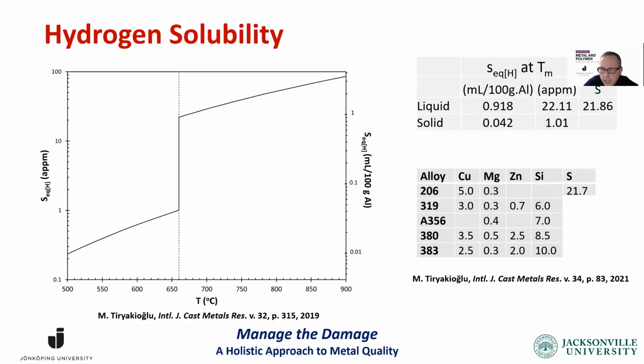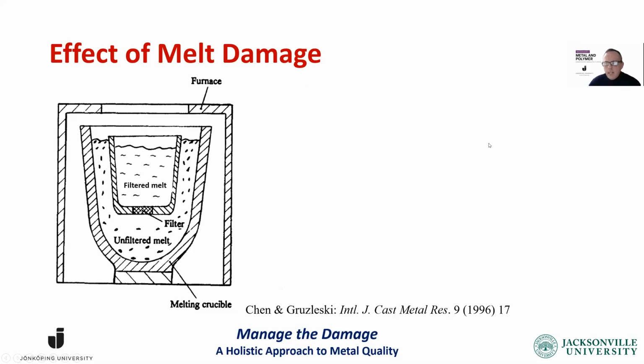When it comes to aluminum silicon alloys like 319, 356, well, we have a much smaller problem. About 3 is what we're talking about. So that gap that we've all learned about is not that big. And when it comes to these die casting alloys, I found something that I never thought I would see, and unexpected. It's lower than 1. What does that mean? The solid alloy can dissolve more hydrogen than the liquid alloy. So why do we need to worry about hydrogen in these alloys? We don't. Okay, let's keep on talking.